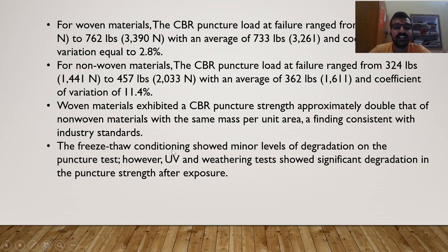The freeze-thaw conditioning showed minor levels of degradation on the puncture test. However, UV and weathering tests showed significant degradation in the puncture strength after exposure.